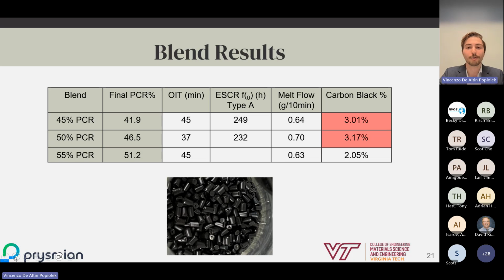Following this, we moved forward with testing our final blends, which as you can see, performed very well, passing almost all industry standards. Of note, our final PCR contents were 41.9, 46.5, and 51.2%. This is slightly lower than what we blended in at, but this makes sense as this is due to the carbon black master batch which was added, as that contains some virgin polymer as well to help with compounding.